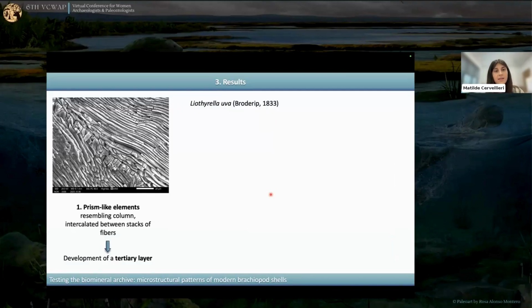Another interesting species is Liothyrella uva, which is an Antarctic species widely studied for its microstructure and its geochemistry. It has always been considered a two-layer species. However, as we can see from this SEM image, there is this layer with prism-like elements which are resembling the columns of the tertiary layer, and this may suggest that this species is also developing a tertiary layer, and so it could be possible that it might be considered a three-layer species.